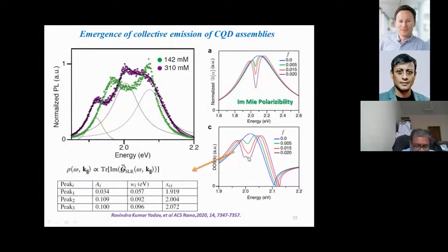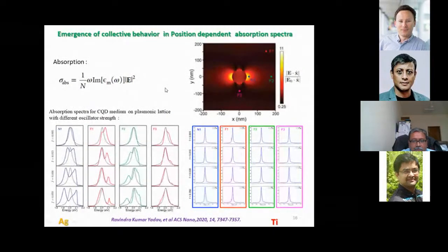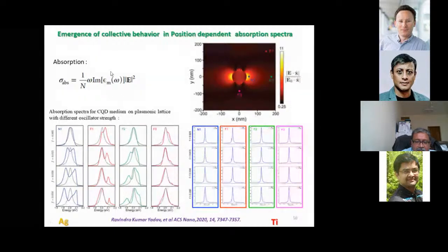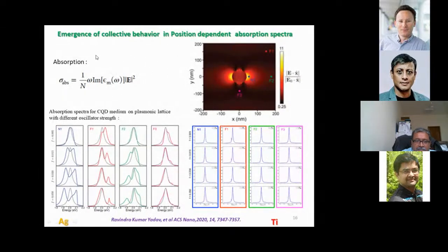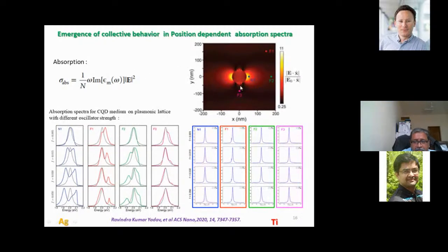So to look at that and to understand that, we do some more calculations, and we even do spatially dependent calculations. This is indicated here: the positions around a particular plasmonic element, a disk or a sphere, and you see for different oscillator strengths. The oscillator strength is small, and then it increases, and you start seeing this feature. These peaks and these positions are indicated here.